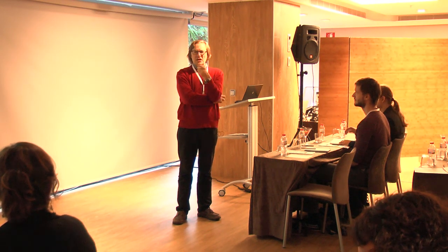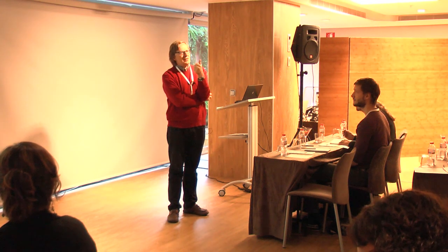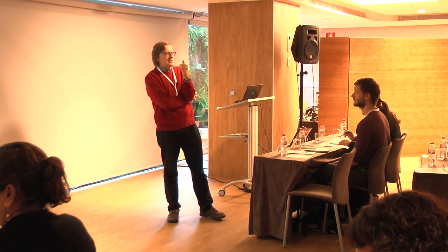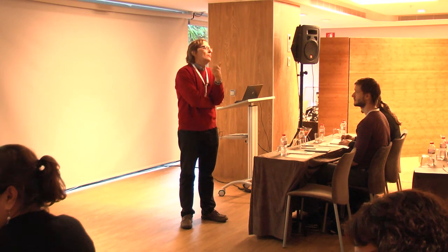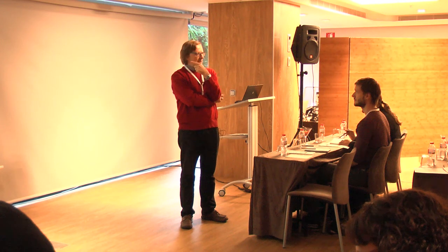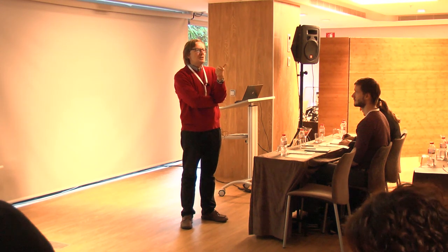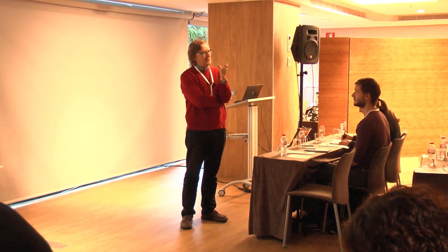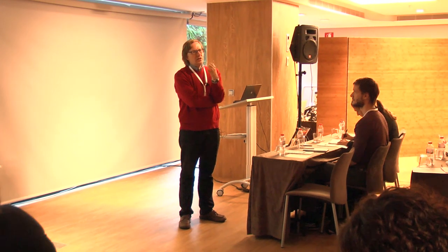I would say that even a study with outdoor cells, because at one sun, it's outdoor. We already discussed it today in the morning, that at one sun, other environmental factors are involved. For example, in our place, first of all, there is much more UV. We cut a bit of UV. The second one is a huge difference in temperature in the desert conditions, between night and day. It's accumulation of water. And this is the first step.